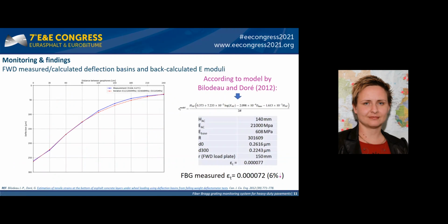When measuring deflections, there is a possibility to back-calculate E moduli and compare them experimentally, which is normally a well-established procedure and provides corresponding results. And having good engineering models to estimate the tensile strain occurring at the bottom of asphalt pavement layers, for example the model proposed by Bilodeau and Doré in 2012, there is a possibility to compare strain values calculated from FWD to those measured from FBG. And here you might see that the correlation shows 6% of deviation.